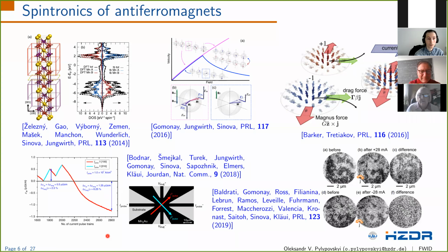The multiple sublattices of antiferromagnets also enable new physics at the microscopic level. This is pronounced in the high domain wall velocities in comparison with ferromagnets, and in the absence of the Walker breakdown. The Magnus force is a well-known inconvenience of ferromagnetic skyrmions. It pushes the skyrmion laterally to the driving direction. In contrast, the antiferromagnetic skyrmion in a two-sublattice antiferromagnet has compensated Magnus forces in both sublattices.